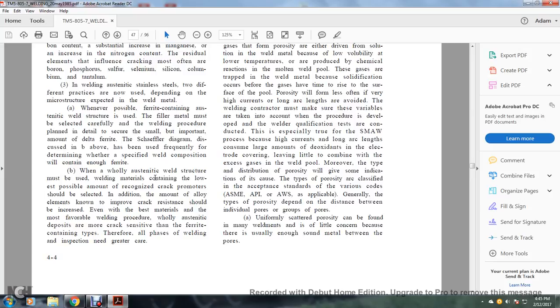Where a wholly austenitic weld structure must be used, welding materials containing the lowest possible amount of recognized crack promoters should be selected. In addition, the amount of alloy elements that improve crack resistance should be increased. Even with the best materials and the most suitable welding procedures, wholly austenitic deposits are more crack sensitive than ferrite-containing ones. Therefore, all phases of welding inspection need greater care.